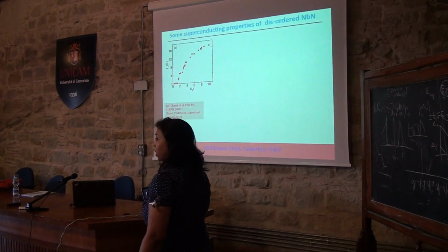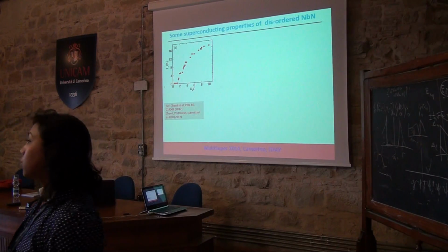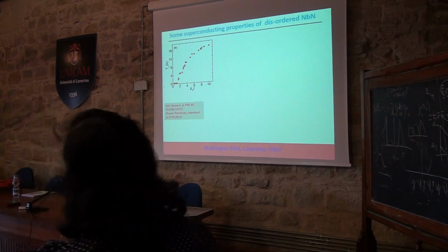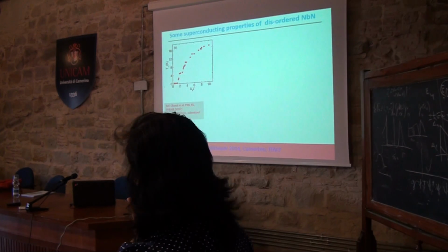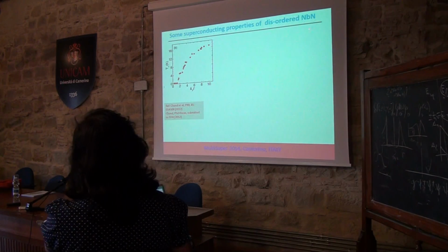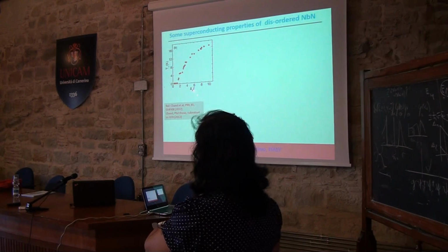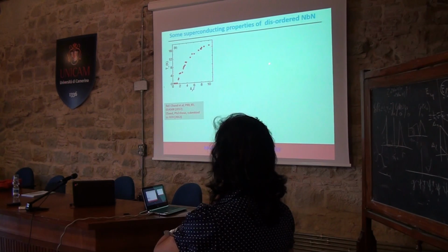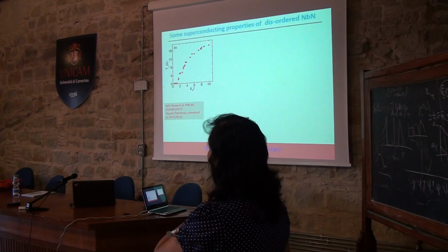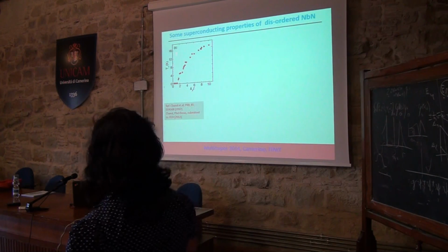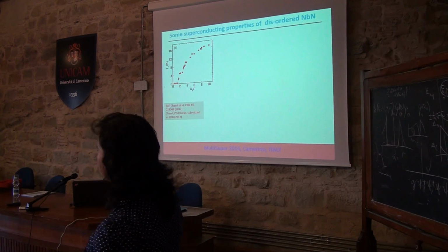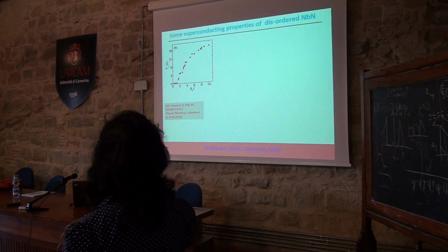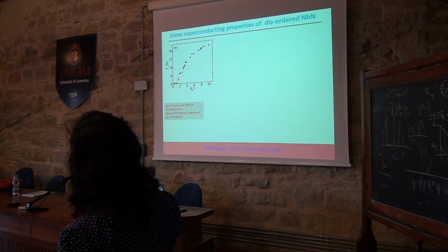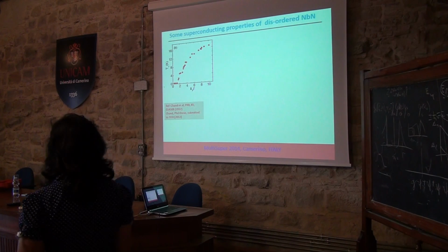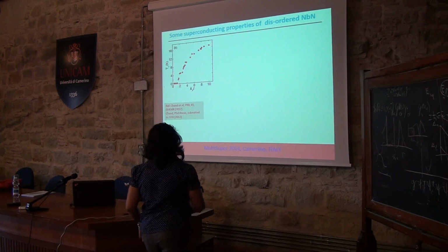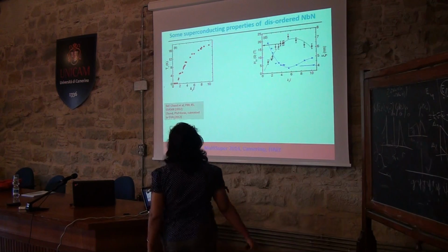A little bit about why we chose niobium nitride. Niobium nitride is a very nice system where you can tune disorder very easily. You can just change the niobium vacancies in these systems, and you can change the disorder of these films. Now with the least disordered film, you get the bulk TC, which is around 16 Kelvin. If you make the films more disordered, with more niobium vacancies, you reduce the TC and you disorder the films. So we have a handle on changing the TC of these systems.